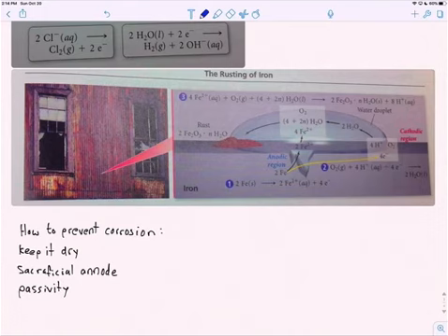The other thing about passivated layers is that they can be penetrated by certain things. I mentioned titanium. Titanium's passivated layer can be penetrated by methanol. Methanol gets right through that layer, and titanium and methanol do not mix. The methanol causes the titanium to corrode very quickly. Same thing with aluminum and chloride.